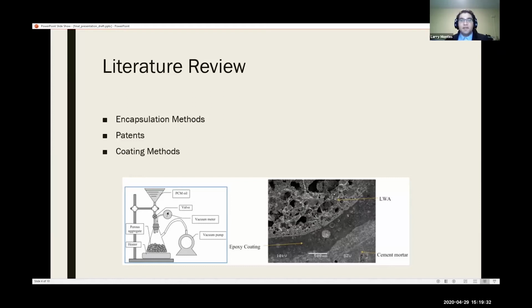The second method is vacuum impregnation, which is similar to soaking, except we have the aggregates and PCM in a vacuum sealed chamber to remove any air trapped in the aggregates and allow more PCM to be soaked. Vacuum impregnation has noticeably better results than direct impregnation as porosity increases. So for example, an aggregate with porosity below 30% will see similar amounts of absorption between both methods, whereas after 30%, the vacuum impregnation method performs substantially better.